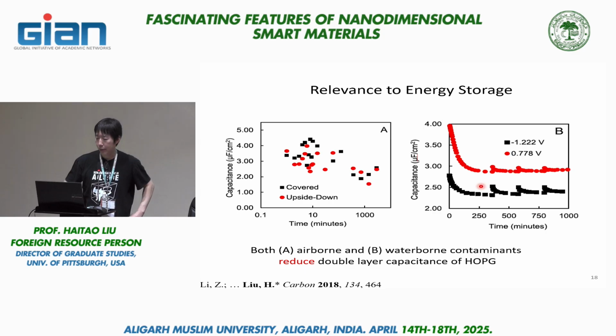Okay. In this case, we also tried some tricks to see if we can drive off the contamination. And what we did is we applied either a very positive or very negative potential. And we were thinking whether we can either electrochemically oxidize those materials or maybe just repel them by electrostatic repulsion. And in both cases, we find quite some interesting recovery.